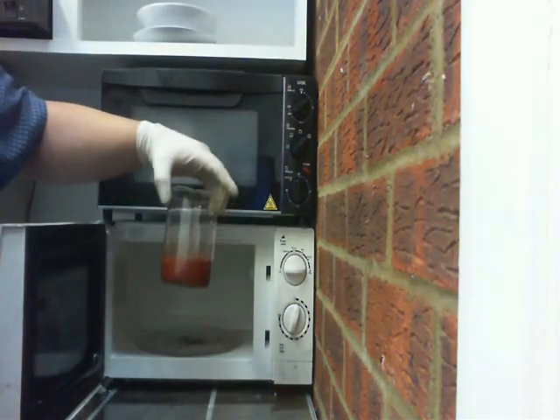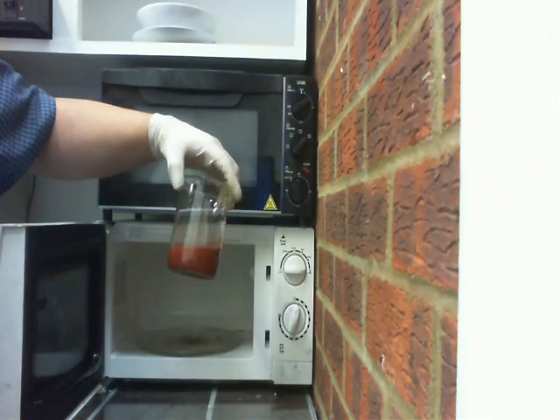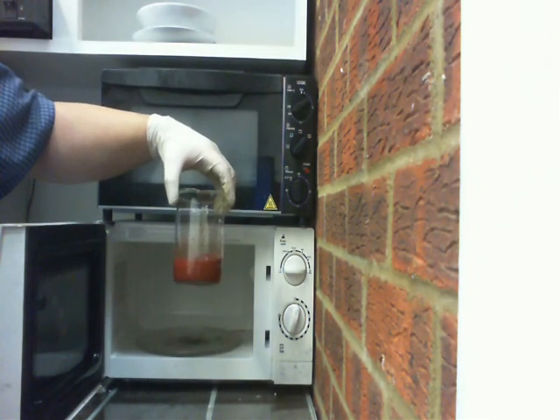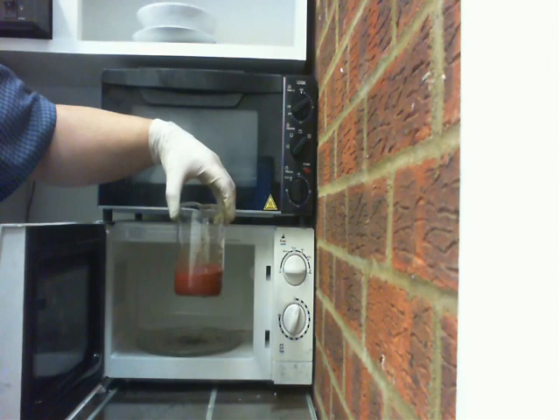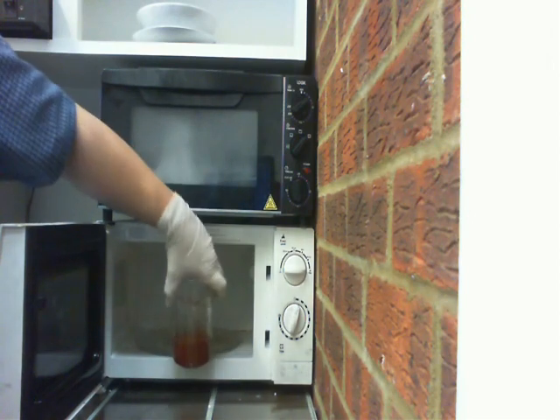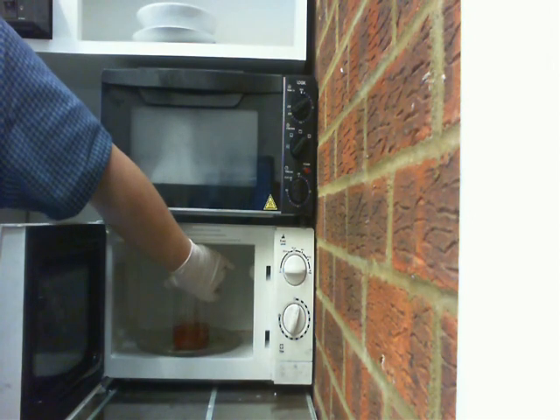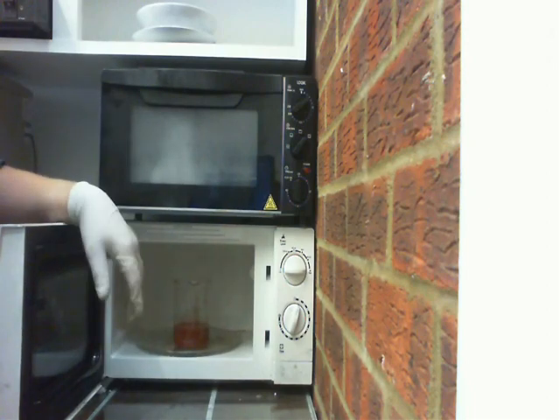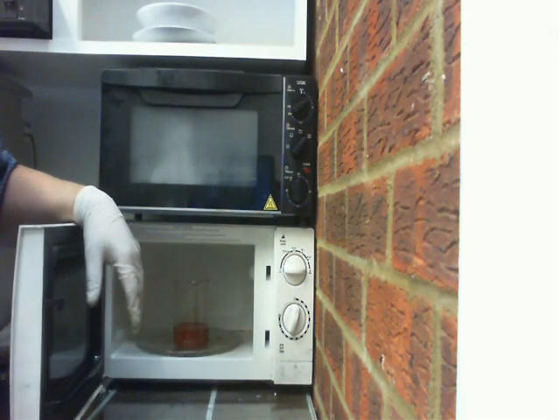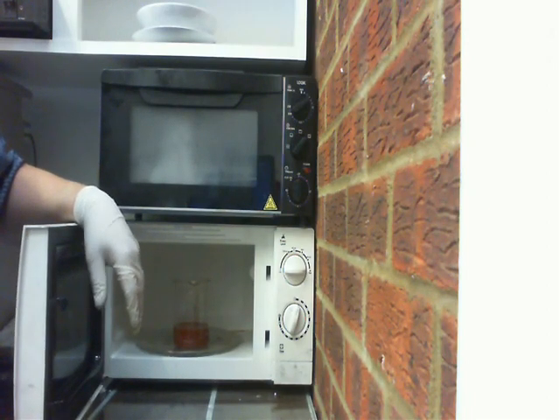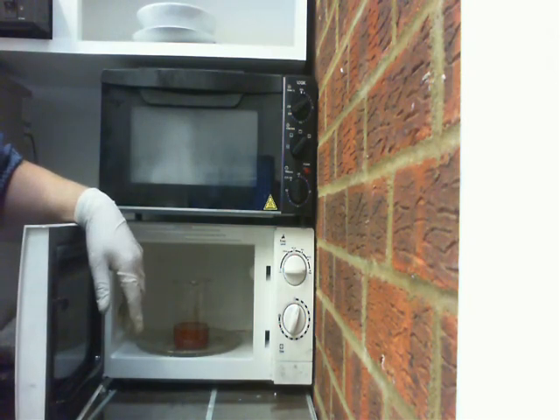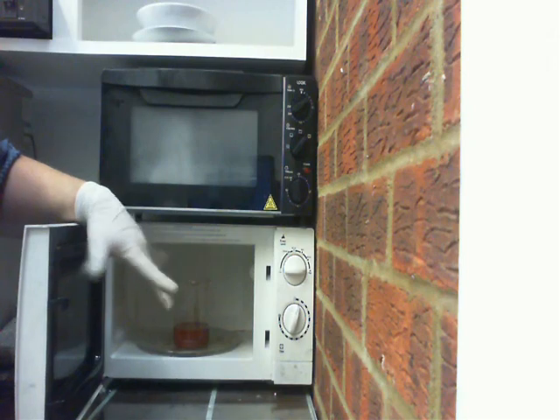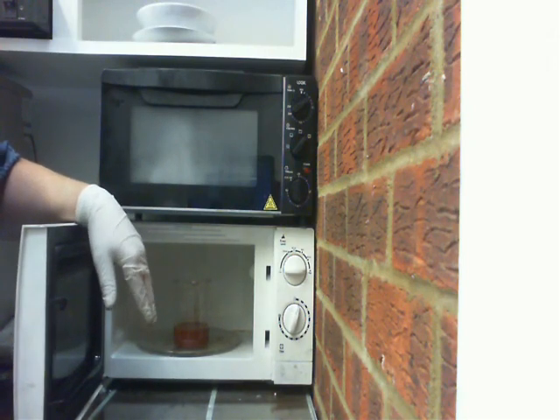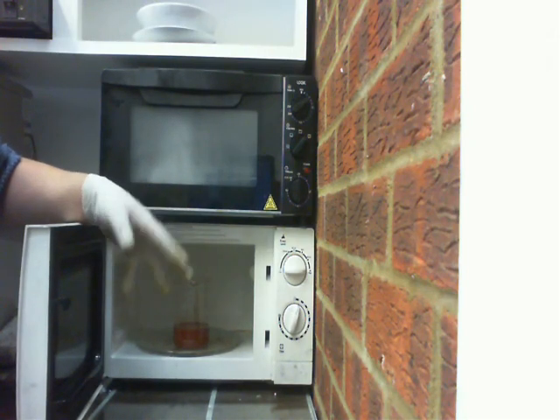So after about 5 minutes, you can see it's gone from its brick red colour to this kind of brownish orange colour. Now it loses water through this process, so about halfway through I add another 25 millilitres of water. Now I'm using formic acid in this. Formic acid is the stuff that you find in your kettle descaler. It's also the stuff that you find in ants. This is 85% formic acid, so you'll notice the gloves. Because if you get this in any cuts, it stings like mad.